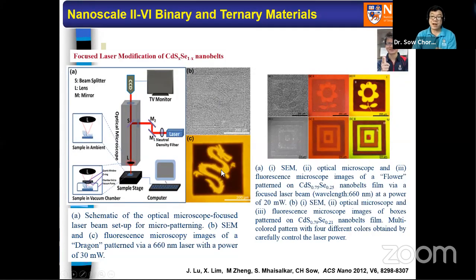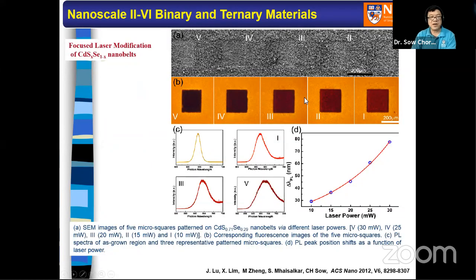Bottom picture: if you now use a fluorescence microscope, shine ultraviolet, for example, onto this sample, it will go through some photofluorescence process and emit fluorescence light. And beautifully, you see, it shows a very nice orange color. And we thought we just destroyed the nanowire. It's not true, you see? You see this particular sample of CdSSe, bottom row, B row, is the fluorescence microscope image.